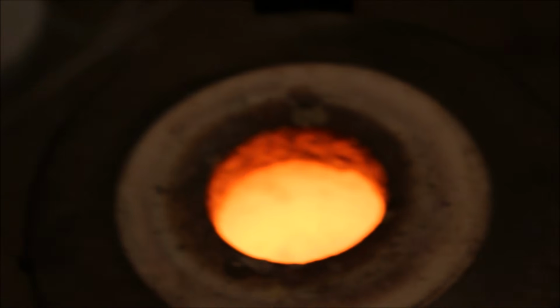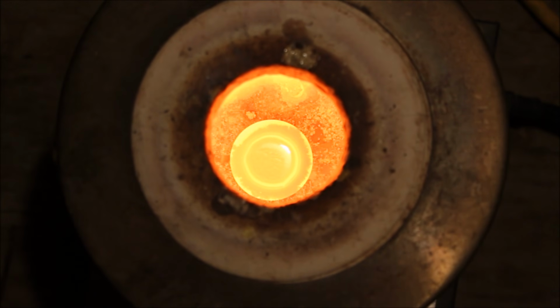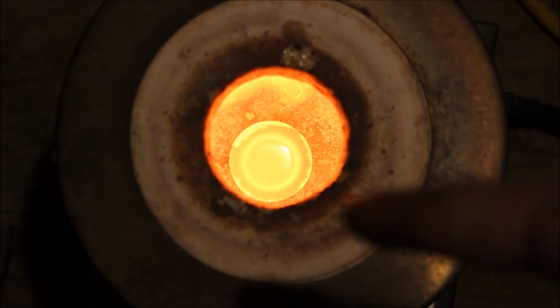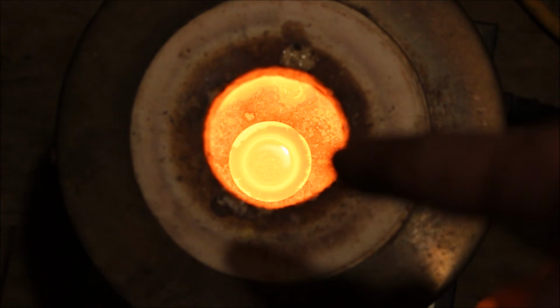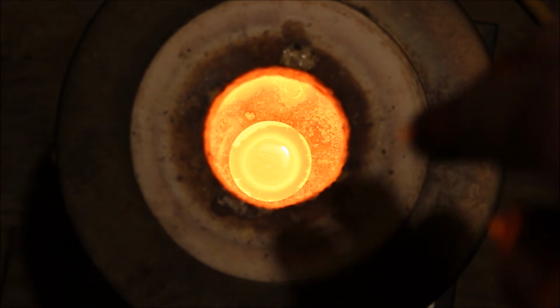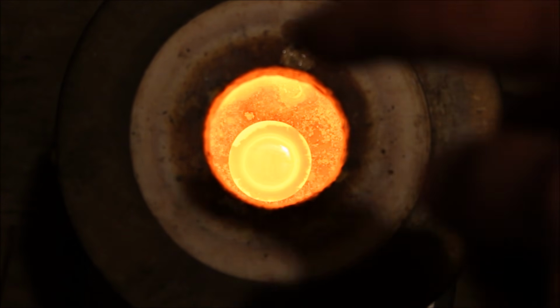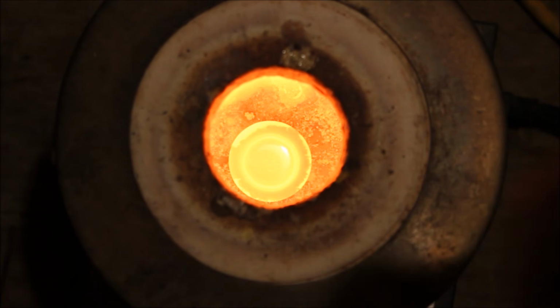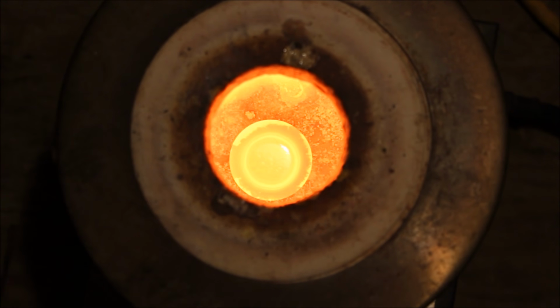Very cool. Alright, so it just passed 1500 degrees. This is Fahrenheit, by the way. And as you can see, the lead oxide is melted and is running off the top of the lead, exposing more lead, which is then being oxidized and then flowing off into the cupel. So it'll just keep doing this probably for over an hour.